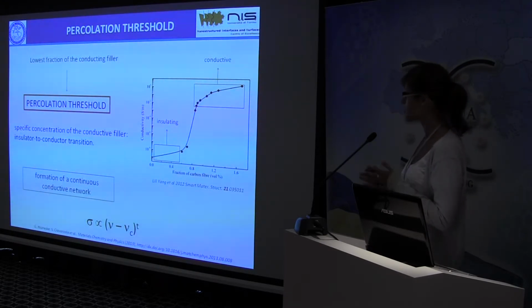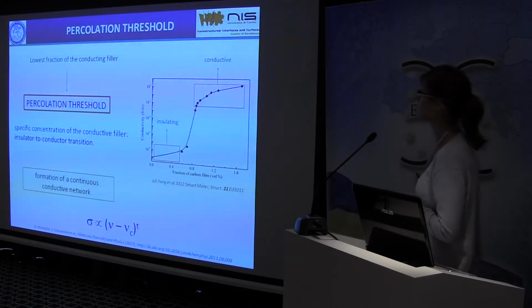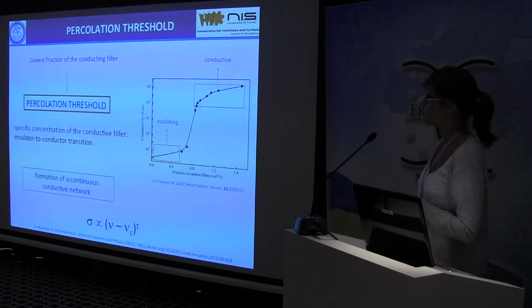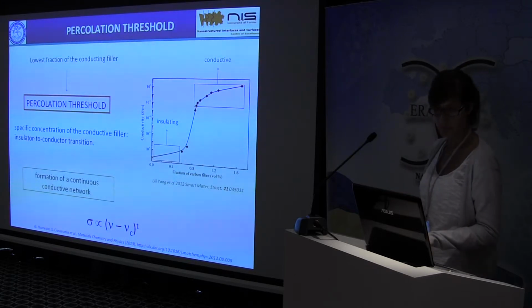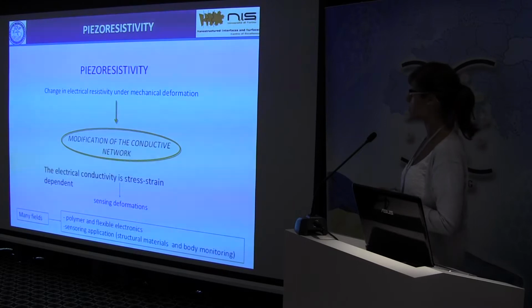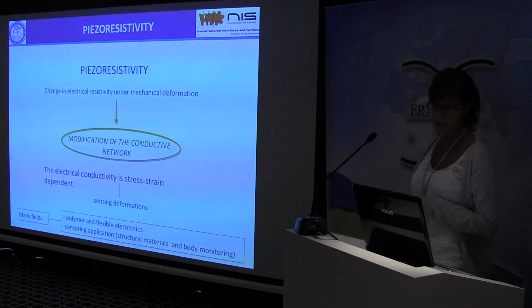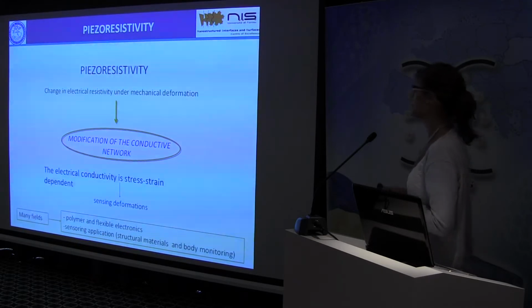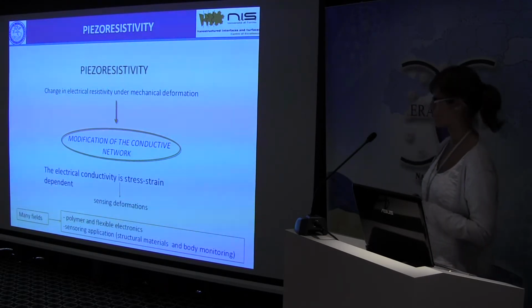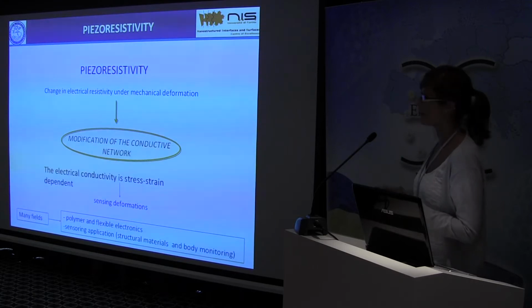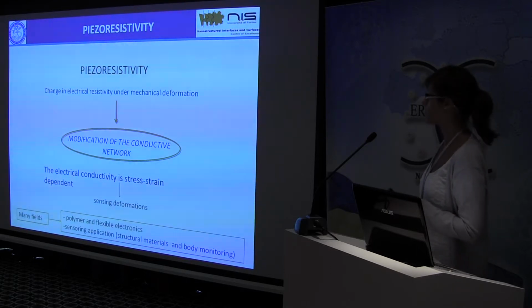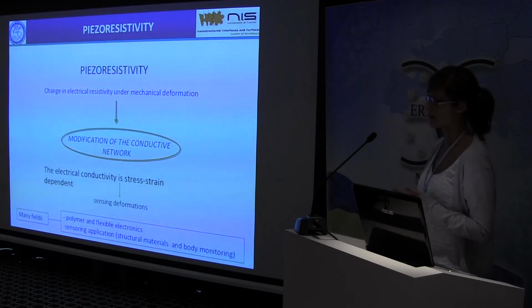The percolation threshold is a specific concentration of the conducting filler at which we can see an insulator to conductor transition because of the formation of this continuous conducting network. An important property of this kind of composite is piezoresistivity, which is the change in electrical resistivity under a mechanical deformation. During this mechanical deformation, there is a modification of the conductive network of the filler, and so the composite shows a change in electrical conductivity.